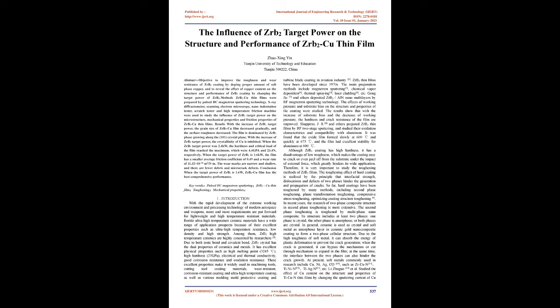X-ray diffractometer, scanning electron microscope, nano indentation tester, scratch tester, and high-temperature friction machine were used to study the influence of ZrB2 target power on the microstructure, mechanical properties and friction properties of ZrB2-Cu thin films. Results: with the increase of ZrB2 target power, the grain size of ZrB2-Cu film decreased gradually, and the surface roughness decreased. The film is dominated by ZrB2 phase growing along the 101 crystal plane. With the increase of ZrB2 target power, the crystallinity of Cu is inhibited.